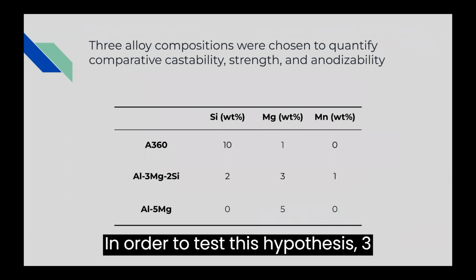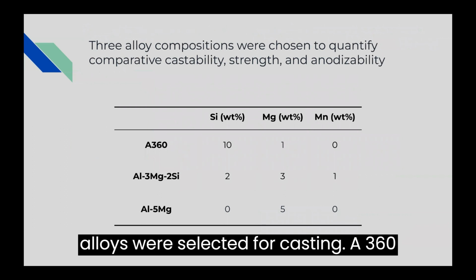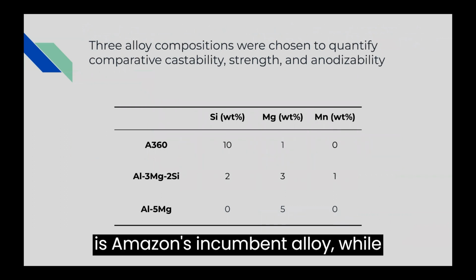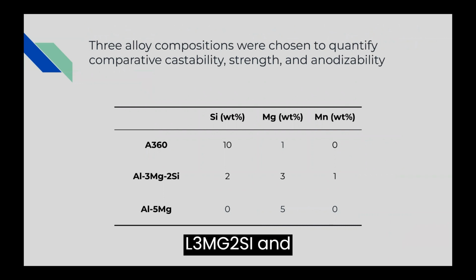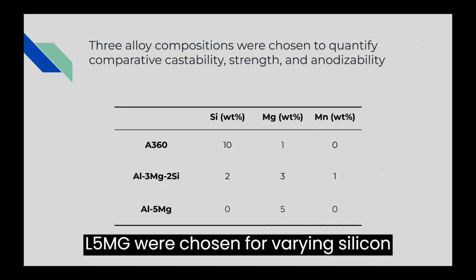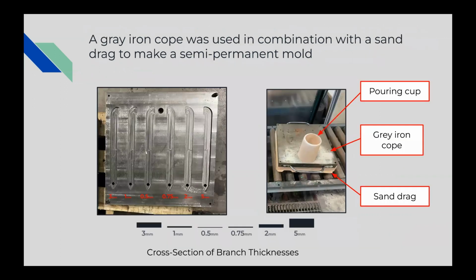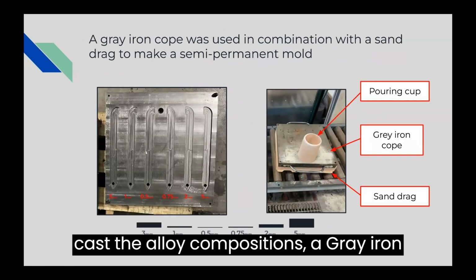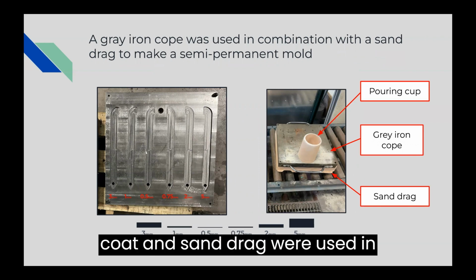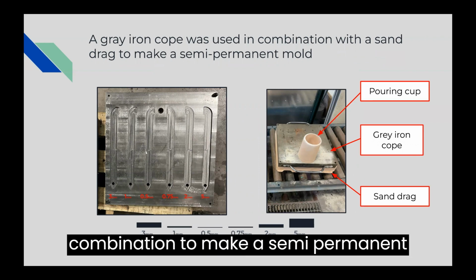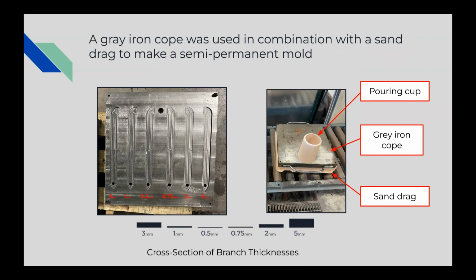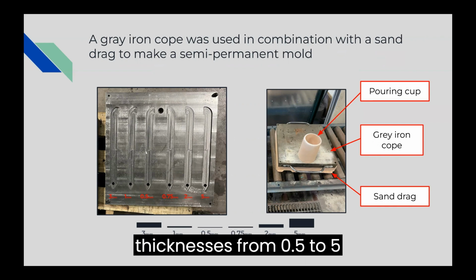In order to test this hypothesis, 3 alloys were selected for casting. A360 is Amazon's incumbent alloy, while Al3Mg2Si and Al5Mg were chosen for varying silicon and magnesium contents. To cast the alloy compositions, a gray iron coat and sand drag were used in combination to make a semi-permanent mold. A tree mold allowed for casting thicknesses from 0.5 to 5 millimeters.